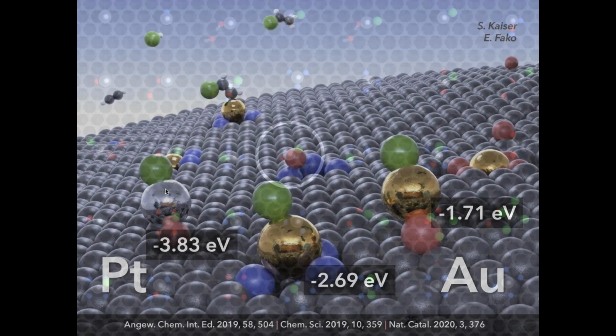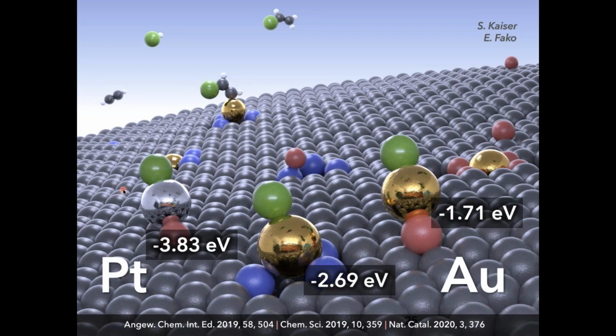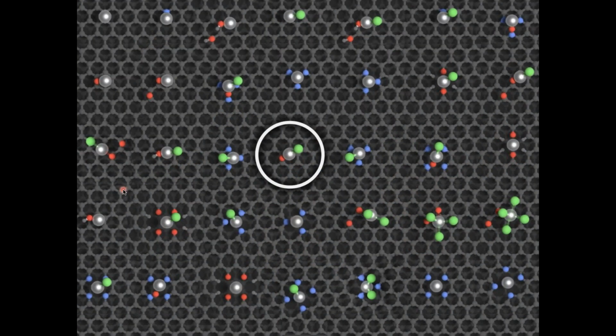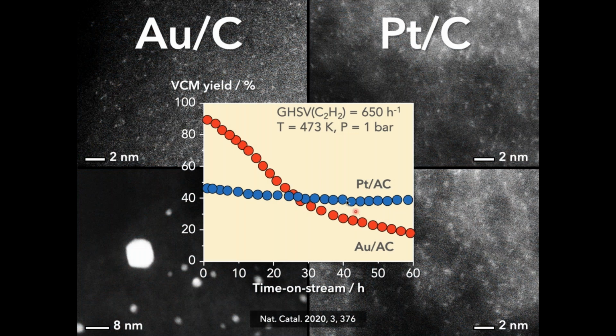This species doesn't come out of the blue. And a speciation analysis was done in order to check the geometry and the environment of the single atom, and the platinum chloride that you see here attached to the oxygen defect in the carbon structure was found to be the most stable and the most active for the reaction. As a consequence, we are just looking at which star has the brightest light that leads to a maximum catalytic activity without compromising stability. And that's exactly what happens with platinum.